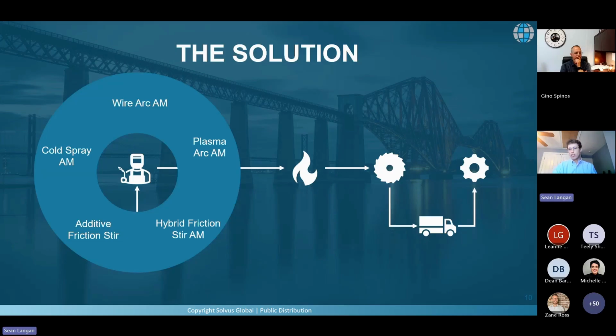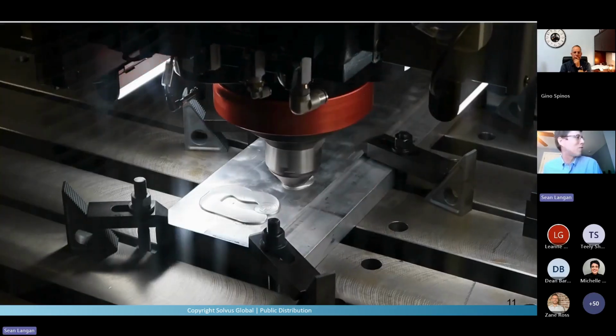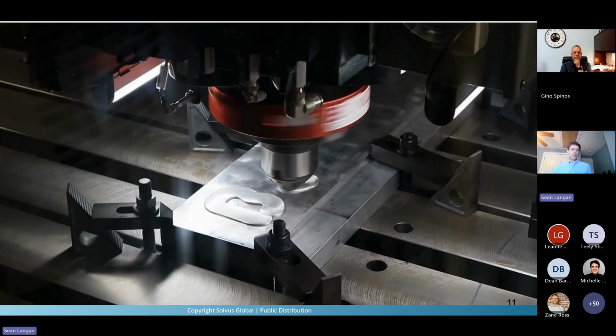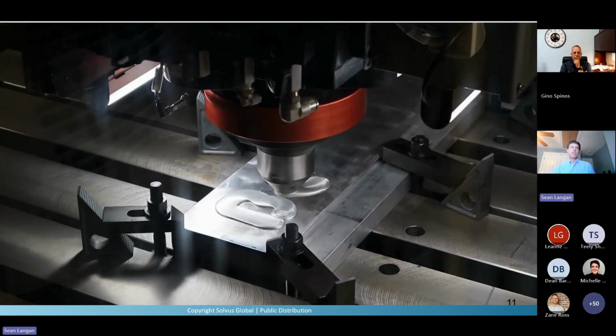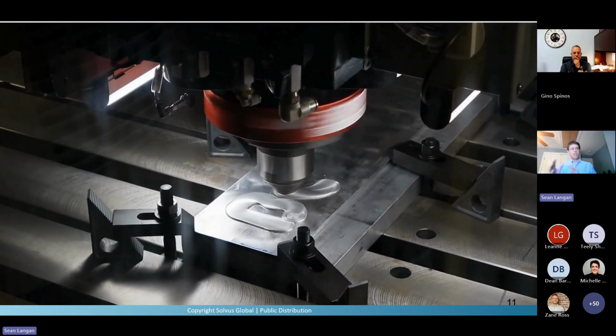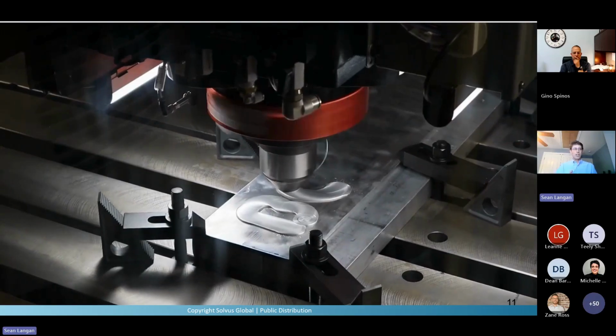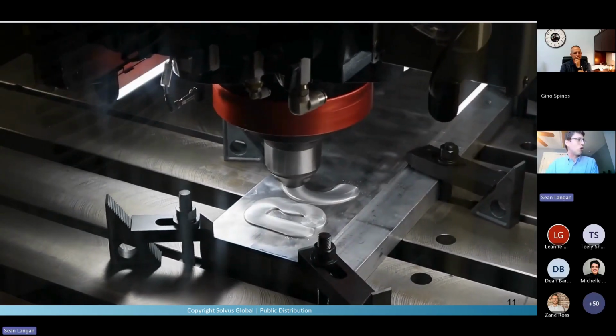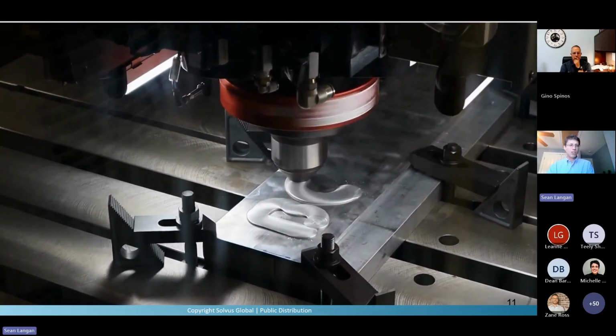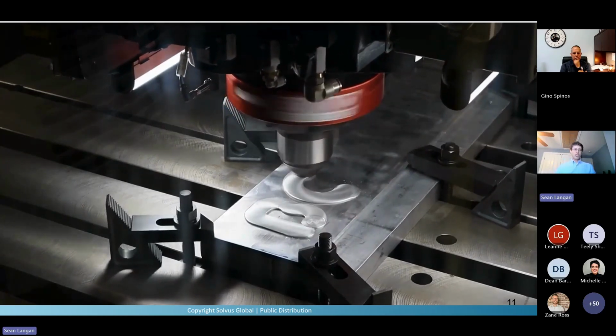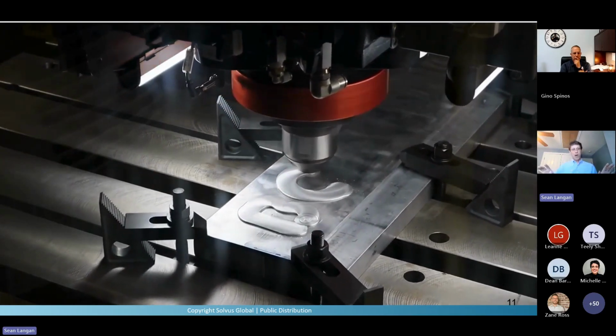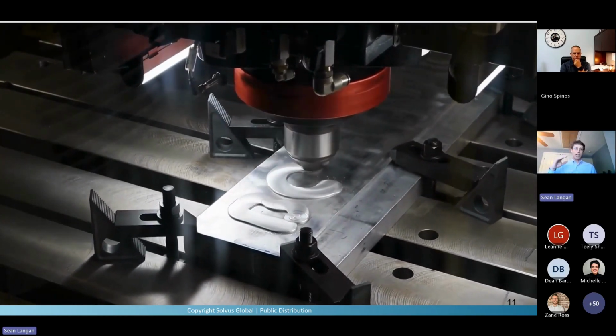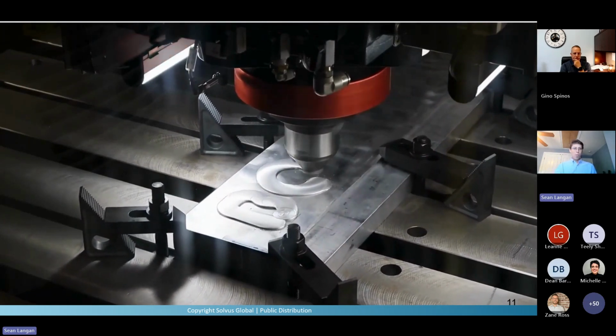But there is one I wanted to show, if only because it's a really cool video. This is something called additive friction stir deposition. It's built upon the background in friction stir welding. Basically what you do is you push material through that nozzle, and by applying enough pressure and heat, you can cause that material to flow out, and you can stack layer on layer with it.